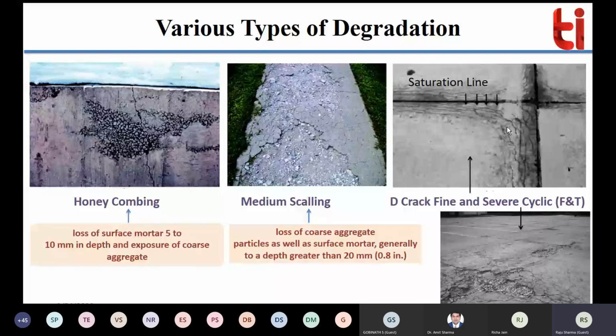During that, tensile stresses may generate around the vicinity of that particle, whether water or ice. Due to that, you can see a number of cracks appearing along the joint line, which generally make a D type of cracking. So generally we say these are D type of cracking. And if you do not maintain or repair this joint initially, then at a later stage it converts into severe failure. The bottom image shows severe cyclic damage. If you do not take care of this kind of degradation at the floor, and it keeps on increasing, the lower image shows the consequences of that.